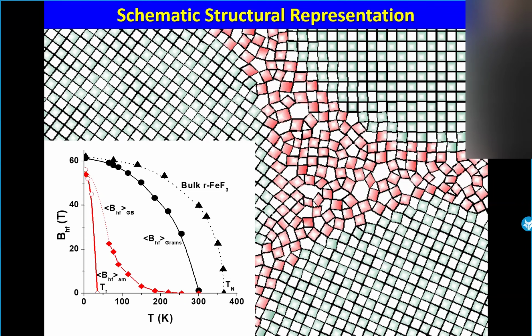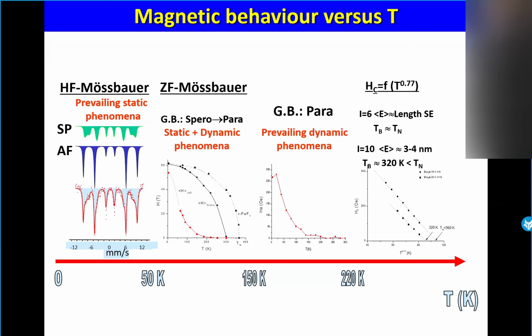So why? If we look carefully, at low temperature, as I mentioned, everything is blocked, grains and amorphous boundaries. Up, everything is paramagnetic, but in between, you have the influence of the grains over the amorphous situation. And it's possible to have a kind of exchange bias phenomenon in between. So the transition between spero and para has to be accompanied because you have static and dynamic phenomena.